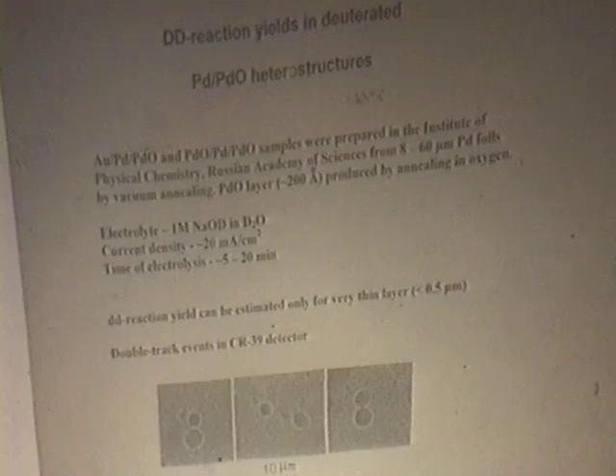According to this calibration measurement, we try to estimate DD reaction yields in different experiments. In this transparency, I present the results of measurement of DD reaction yields in deuterated palladium-palladium oxide-gold structures. The samples of these structures, palladium oxide samples, were prepared at the Institute of Physical Chemistry, Russian Academy of Science, in Dr. Lipson's group.